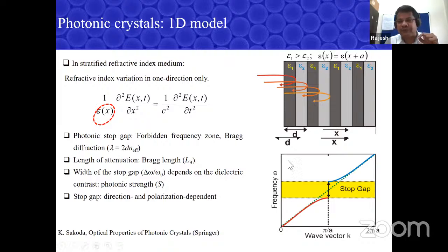If I give you a sample like this and you launch a frequency of light within this yellow region, the light cannot propagate through the sample. This absence of propagation, where the light is not allowed to pass through, we call a band gap, frequency gap or stop gap. I use these interchangeably in the talk; they all mean the same. What happens to the light? It just decays into the structure. And you can have this periodicity in 2 directions and 3 directions.